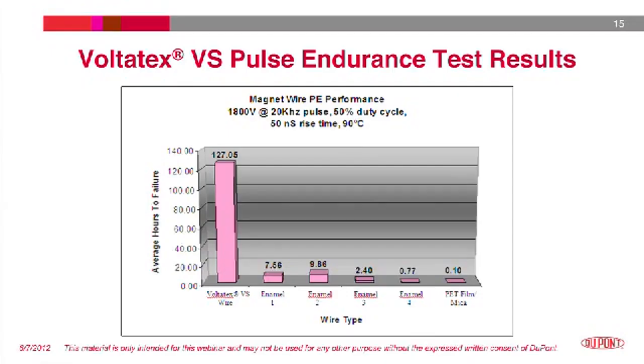For most inverter duty motors, small, round enamel coated wire is used. In one specific case, an engineer was designing a low voltage motor for an application where the threat was an inverter which creates dV/dt, which accelerates degradation of the wire enamel. We evaluated this threat using a 20 kilohertz pulse with a 50 nanosecond rise time.